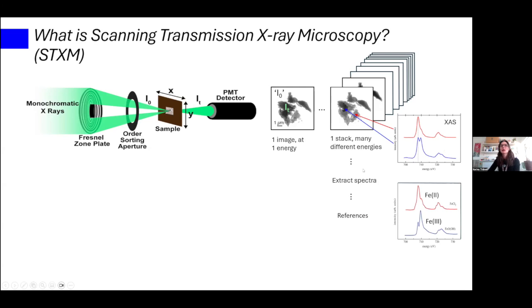Right, then what do you do? Well, you can normally compare them to references. So if you are looking, for instance, at the iron edge, you may have some inkling that you're looking for different oxidation states of the iron in your sample, for instance, Fe2+ and Fe3+. And then you can have references from like Sigma Aldrich that you prepare on a similar sample slide, and you run through them as well, so that you know what an Fe2+ spectrum would look like and what an Fe3+ spectrum would look like. And then you can compare them to what you find in your actual sample.